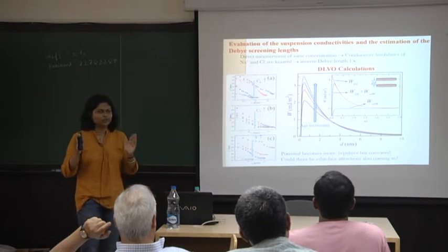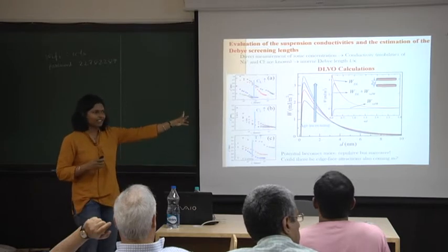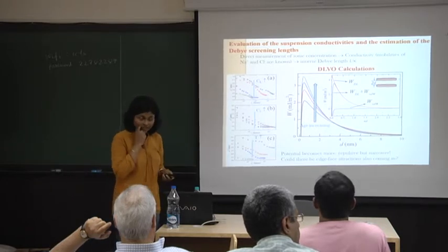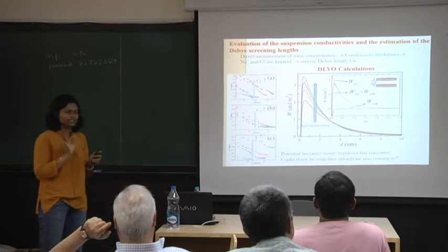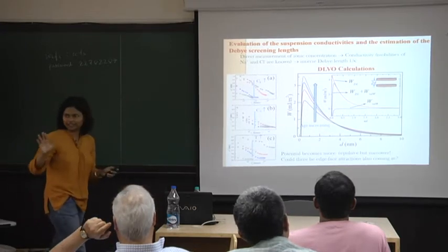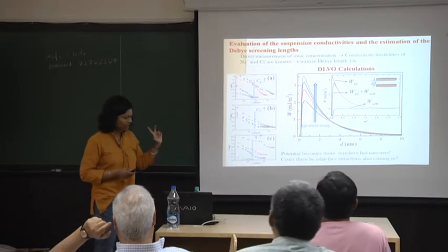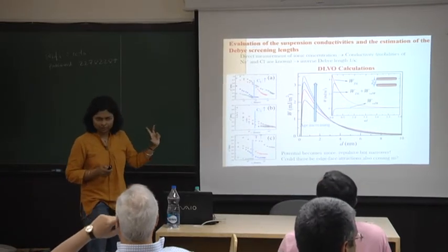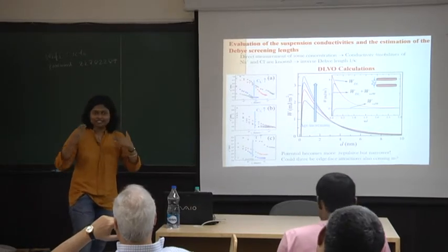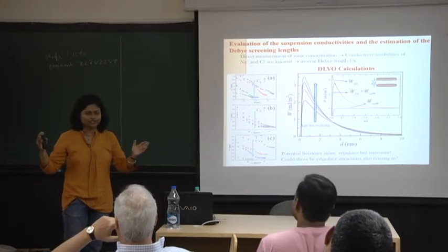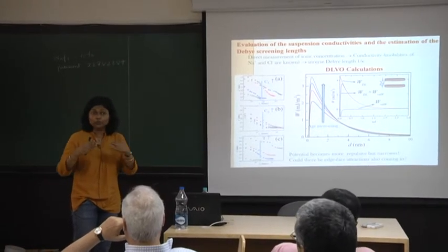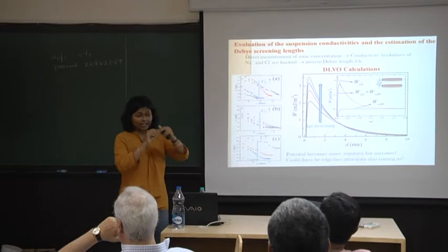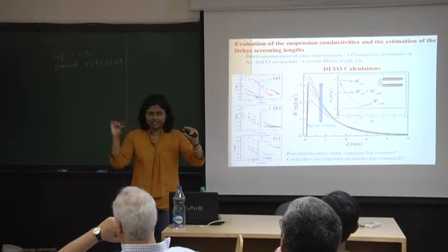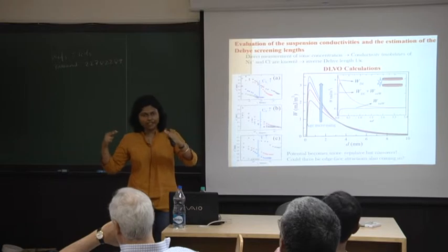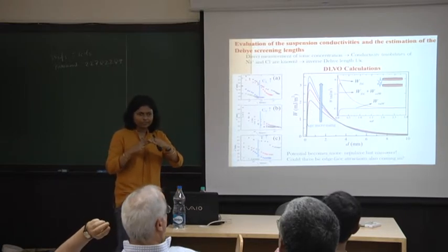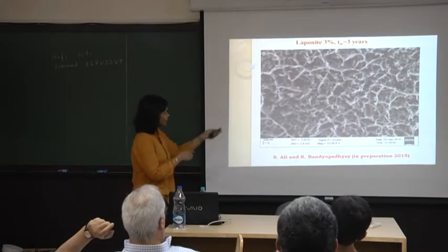It's all an extrapolation. You say this hardly looks like it's really narrowing, and I agree, the percentage increase is very small. However, one of my students had left a sample of laponite which was 3 years old. You'd expect that with time, as the sodium ions come out, the particles have time to move if you keep them for a very long time. So you have these weakly positive edges and these negative surfaces. The positive edges may just attract the negative surfaces. And this is the data.